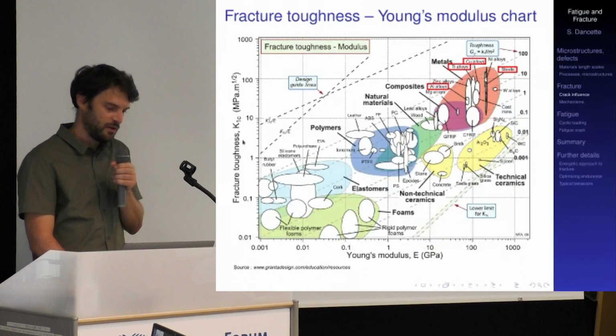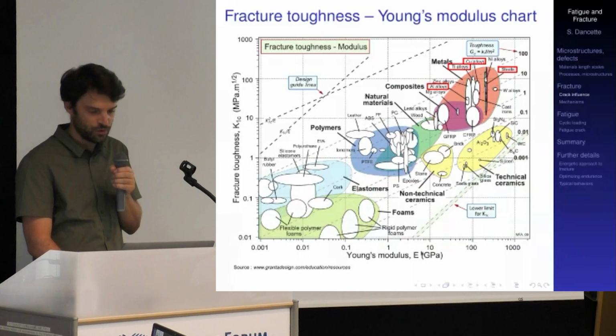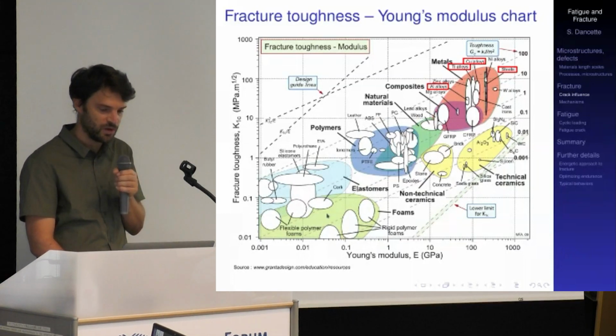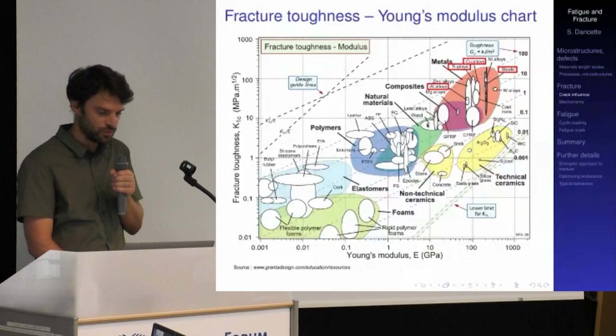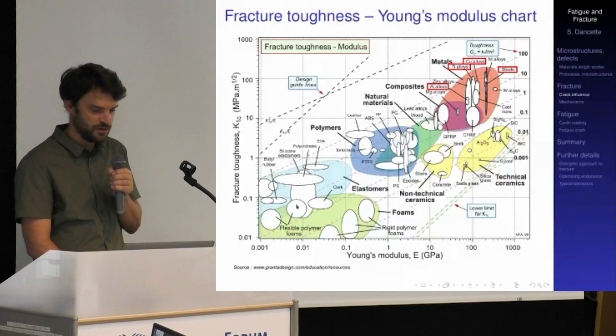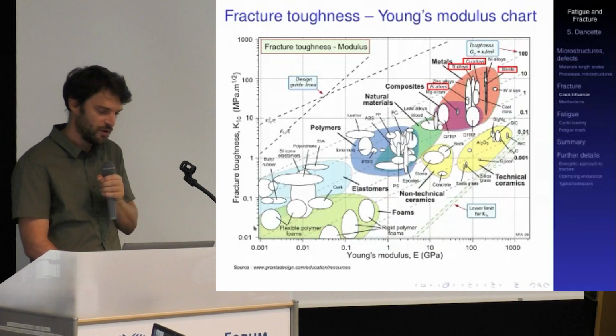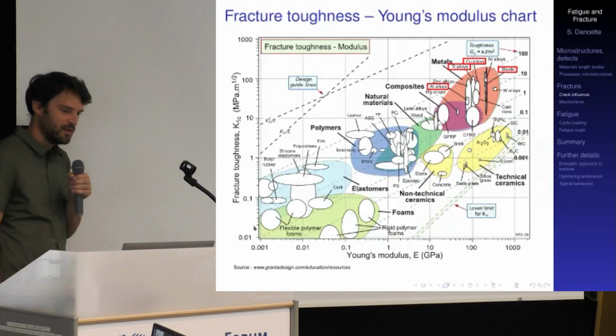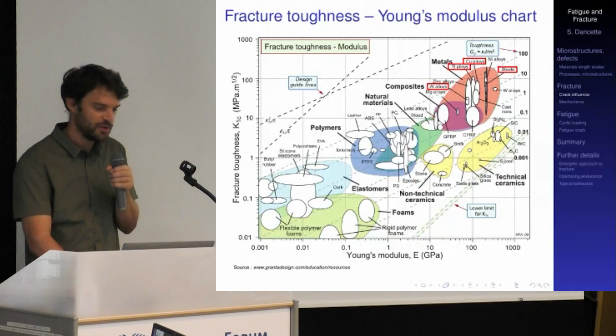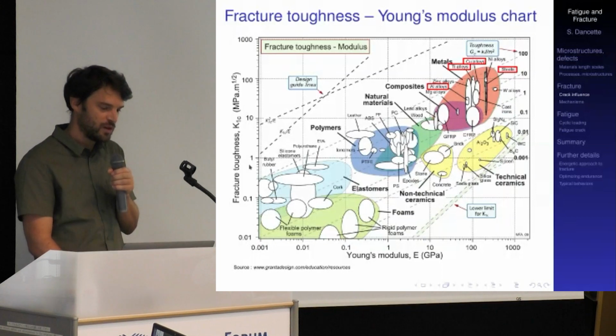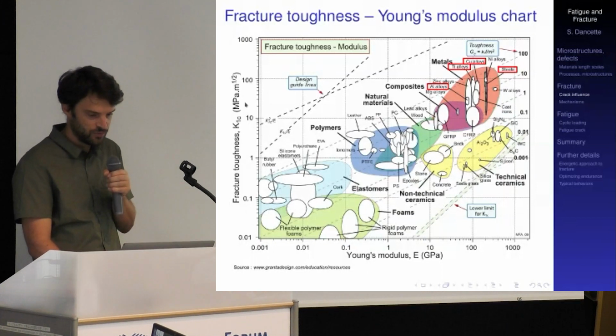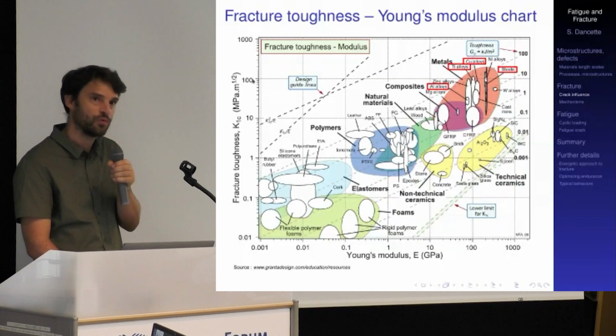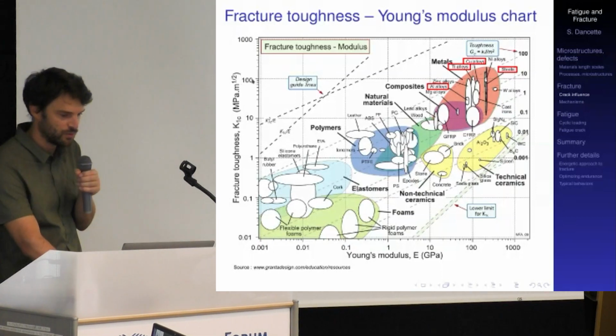So now we have an overview of these values of fracture toughness here. The vertical axis is the fracture toughness as a function of the Young's modulus of several different classes of materials. We have the metals here on top, and the elastomers and the foams at the bottom. You can see that this fracture toughness K1C can range over several decades in order of magnitude, from lower than 1 megapascal square root meter to, in the case of metals, more than 100 megapascal square root meter.